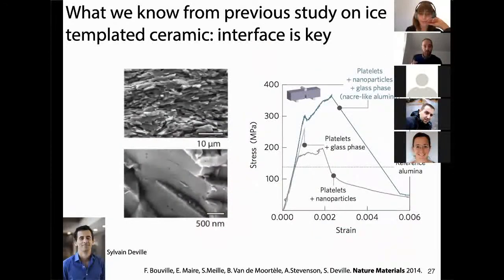So this is actually a bit of an old story now. These materials were developed during my PhD with Sylvain Deville at Saint-Gobain. What we found out at that time, with samples made with a completely different process, is that at the interface, instead of trying to put another type of material, a polymer or metal, if you just put a mineral phase, in this case a glassy phase, silicon oxide based,